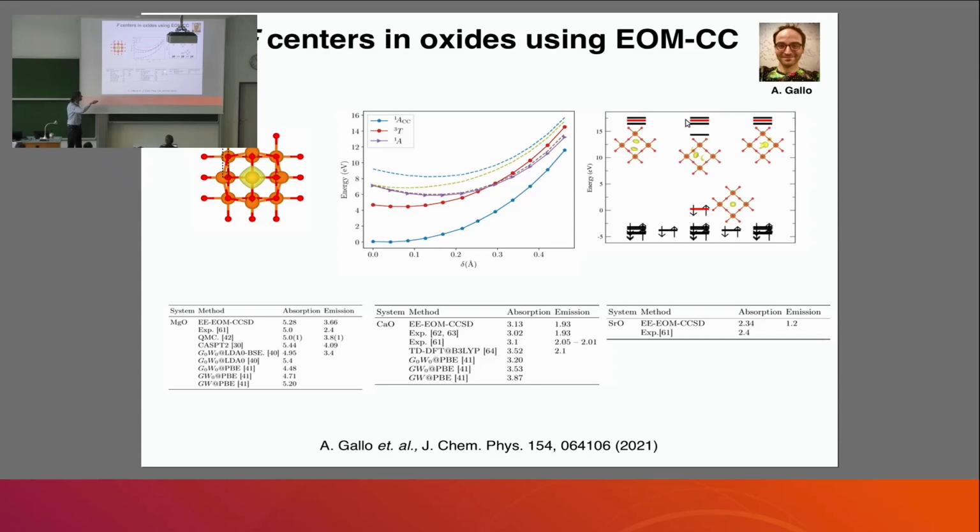And it turns out that for magnesium oxide, the peak that is assigned to this emission has long been a debate over different processes. And it's most likely not really an emission of the F center in the magnesium oxide, because in this system, magnesium oxide has the shortest bond length, the shortest lattice constant, and it's difficult actually to really say that this transition from the excited to the singlet state does really occur. It's much more likely that before it can de-excite, it's actually going into a charged state due to this excitation.